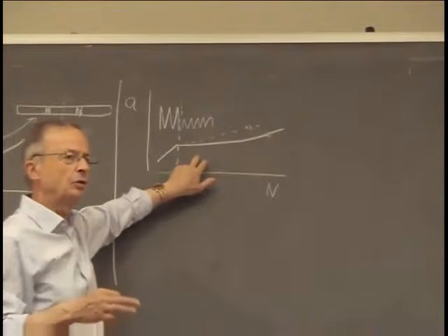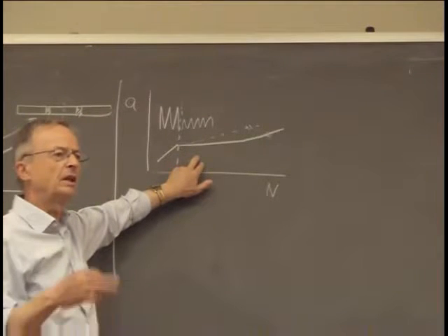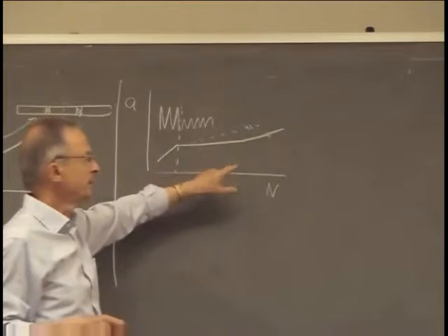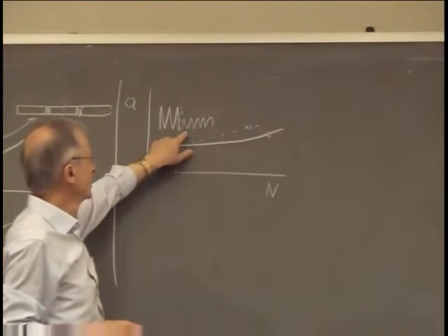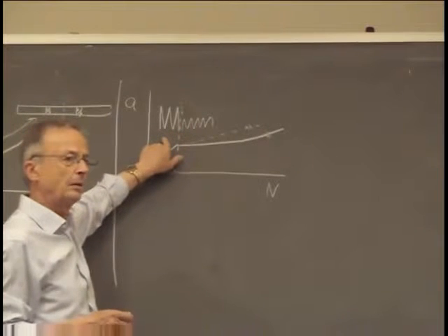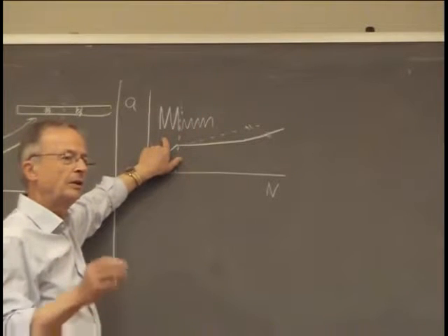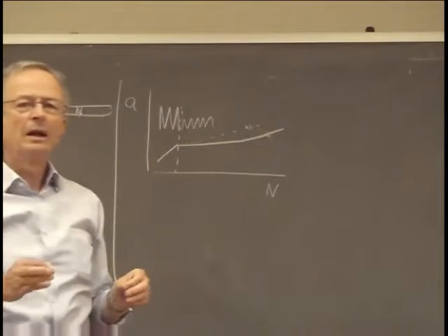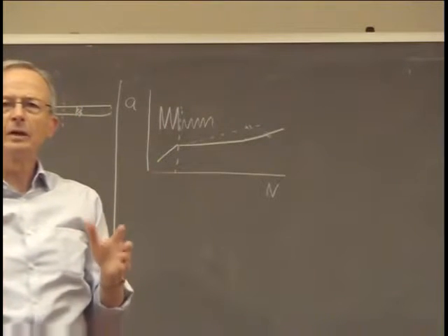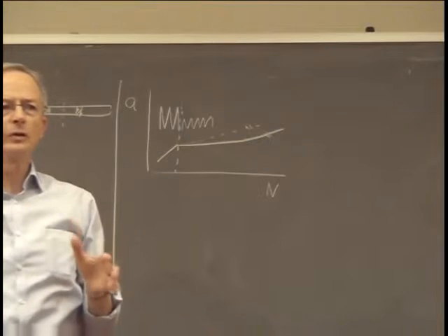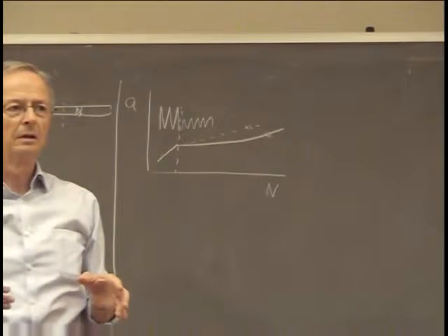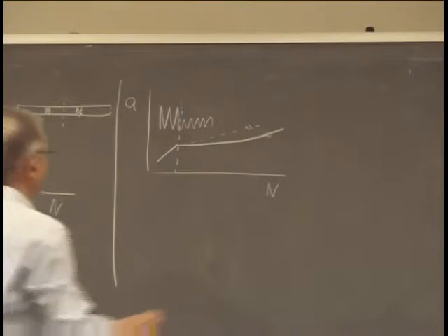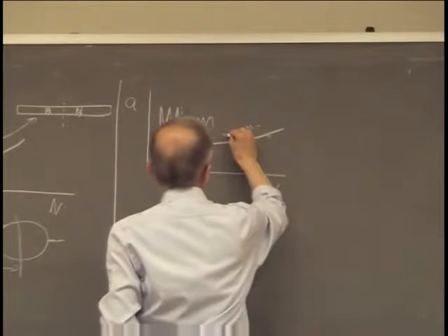Obviously, we have an interaction or a history effect. People call it load history, because we will now see the reverse effect when we go from a small amplitude to a bigger amplitude. We have a different effect, and this shows it really matters in what sequence we apply certain load cycles or blocks of load cycles. It's the order that matters. So here we have a delay, which can be substantial, here.